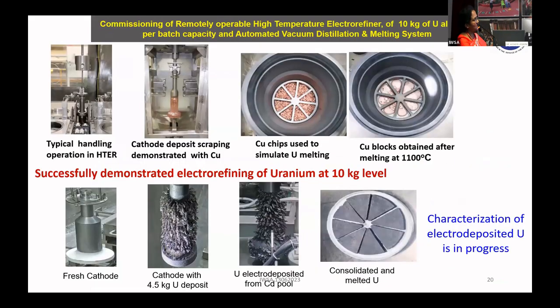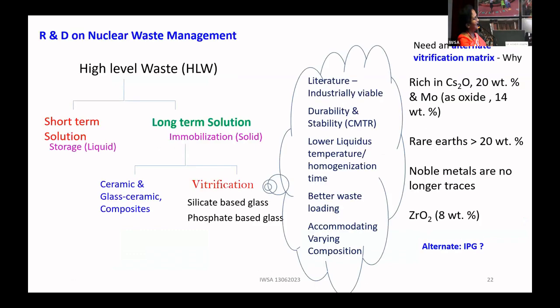And before we start with uranium, we always do cathode deposition with copper. You melt it, you form the copper blocks, and you can see the fresh cathode shown here, and the cathode with uranium deposit, uranium deposited in the cadmium pool. All the things have been consolidated. And next on the R&D, another 5 minutes I'll be able to.